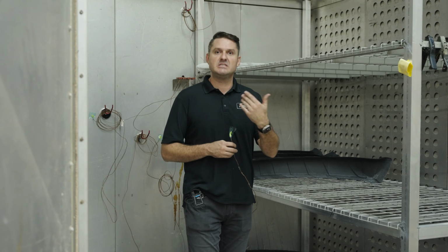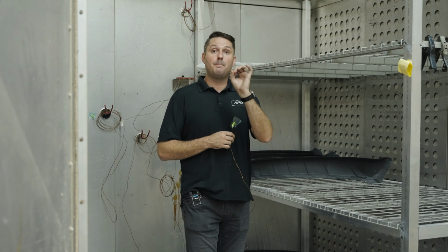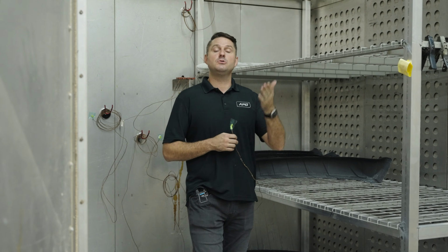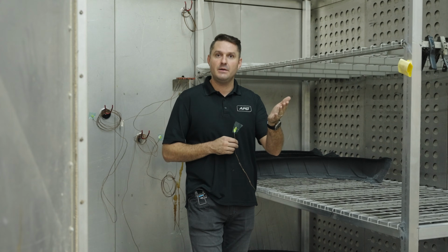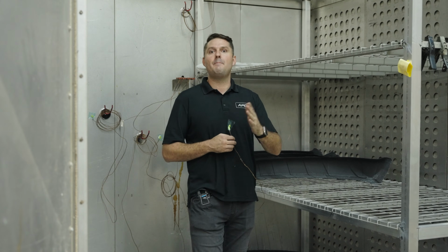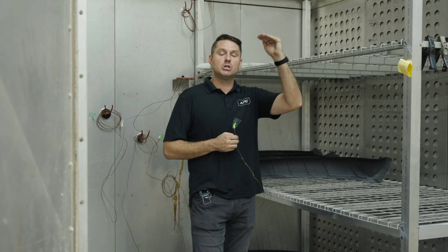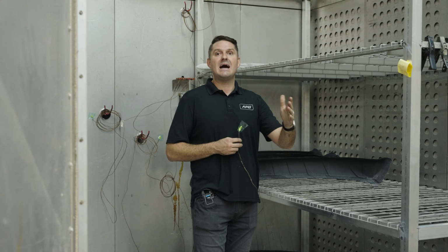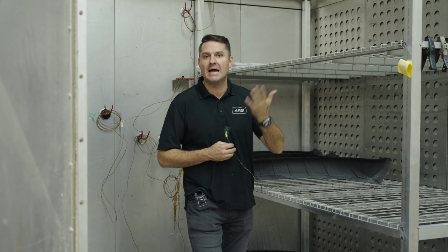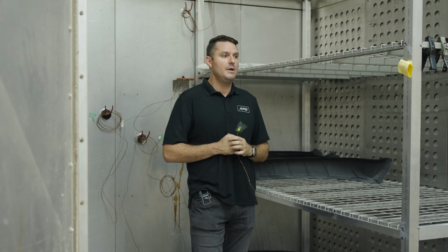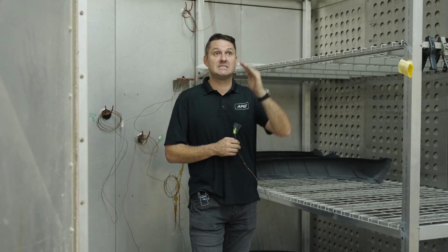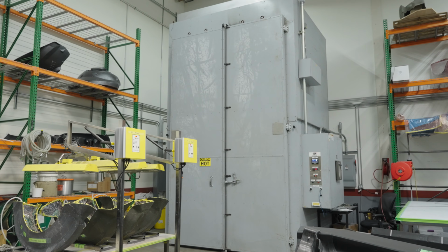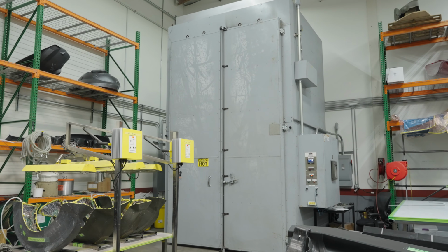Typically, it's 20 degrees Fahrenheit ramp up per 60 minutes, up to 280 degrees Fahrenheit. Hold that for about 8 hours, and then slowly cool down to ambient temperature, 80, 90, 100 degrees, whatever it happens to be. Once that oven cure cycle is complete, you've now finished all the composite manufacturing process.